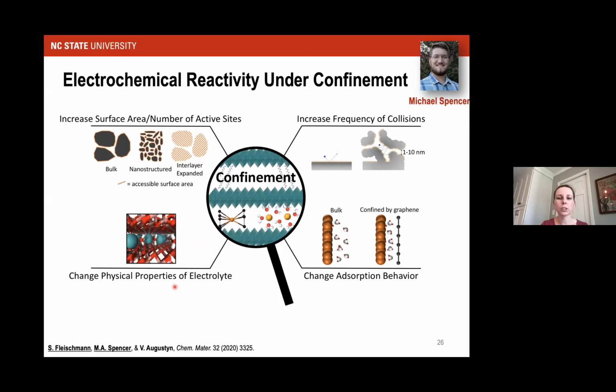So solvation is different under confinement. For example, viscosity is different under confinement. Hydrogen bonding of water is different under confinement. And we think that particularly for energetically challenging reactions, which is what we oftentimes want to do with electrochemical catalysis, this could be a very interesting knob to tune. And it's really a question now, I think, of going after the systems that can help you demonstrate what a lot of these computational studies seem to be showing.